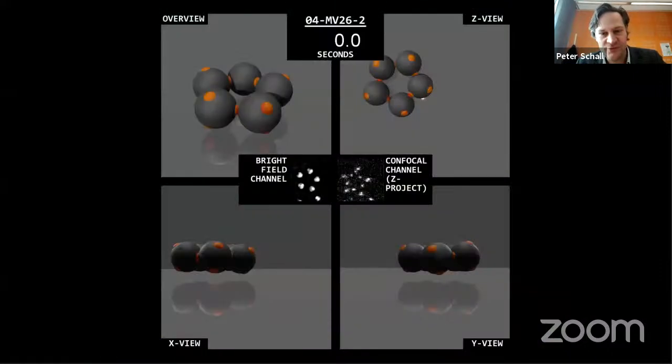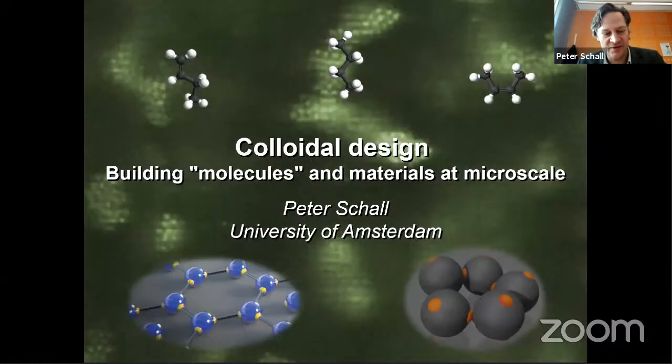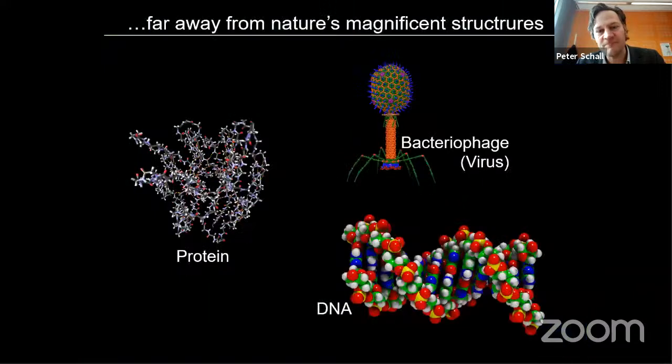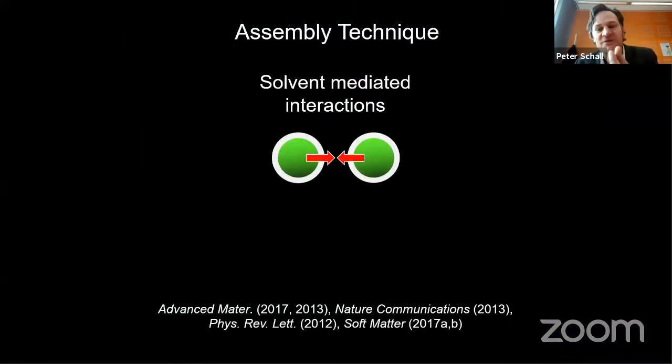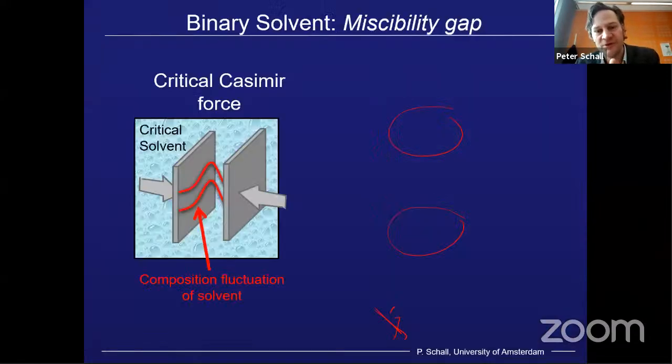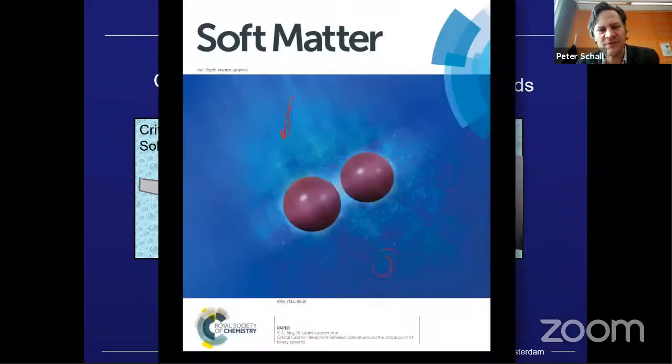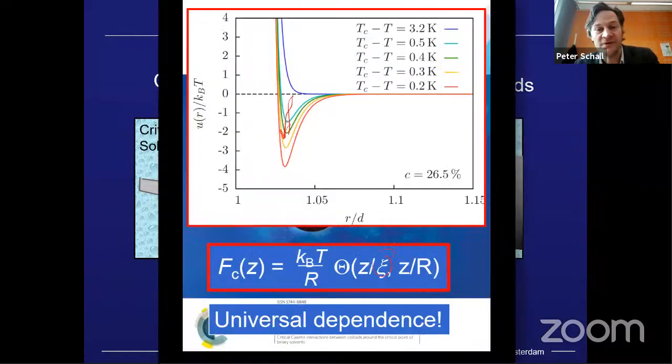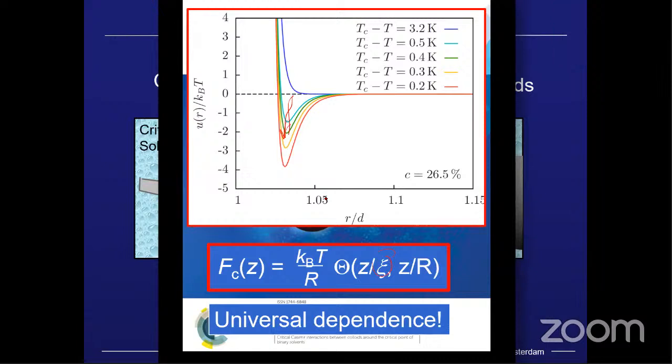Let me just try to go back a little bit, because the range of interaction we have in our system, because we are still some distance away from the critical point, is actually quite small. So if you look here at the interaction potential, R is scaled by the diameter of the particles, which is, let's say, a micron or 2. You see that this is of the range of the potentials of the order of 20, 30 nanometers, right? At this distance to the critical point.